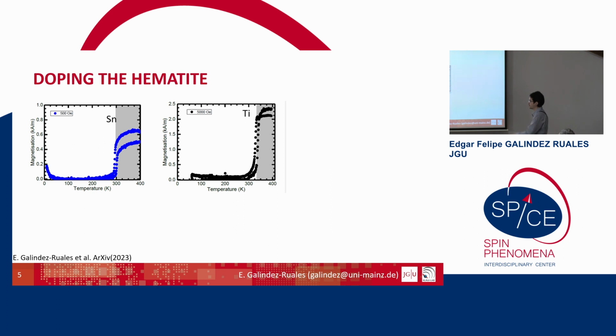There are a lot of nice papers about the theories of what is happening with this doping and the increase of the Morin transition, and I will not go into the details now. The case is when you dope the hematite with Sn, you have a Morin transition of 300 for thin films of 150 nanometers, and in our case, we have a Morin transition around 320 Kelvin. So the Morin transition is higher than room temperature. So we will have the easy axis phase at room temperature, which is something that someone mentioned as a perfect candidate to be a device, right? We have the altermagnetic properties at room temperature.